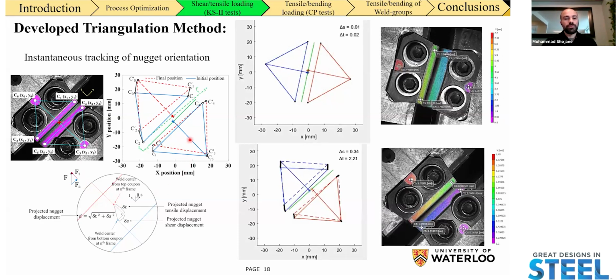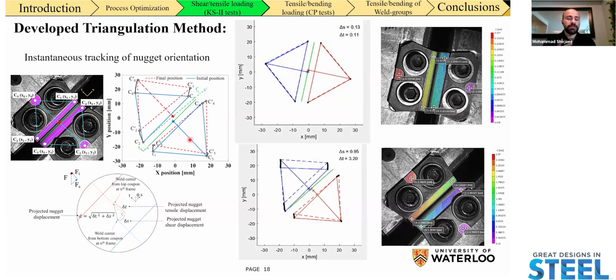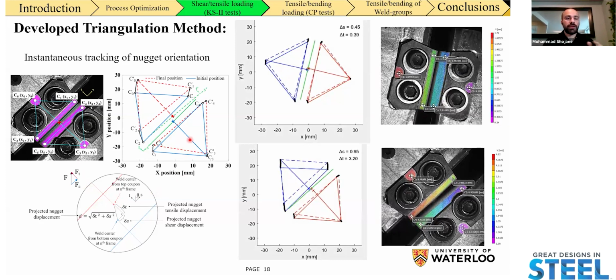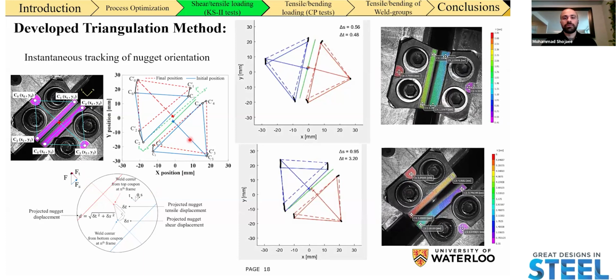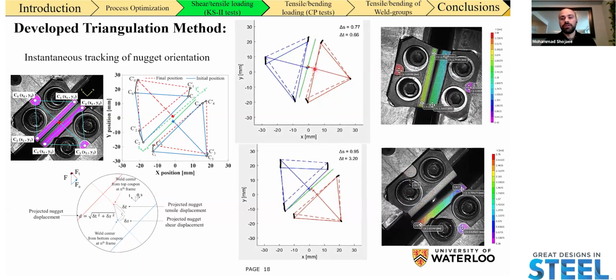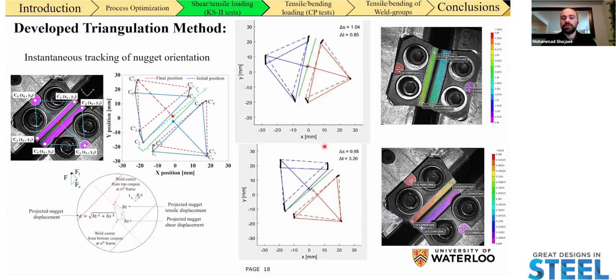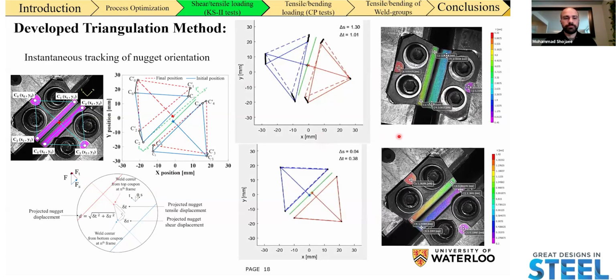And this way, we're able to track the displacement of the weld in shear direction or tensile direction, and we can at the same time track its orientation throughout the test, as I've shown in the videos on the right-hand side that are synced with the experimental footage.